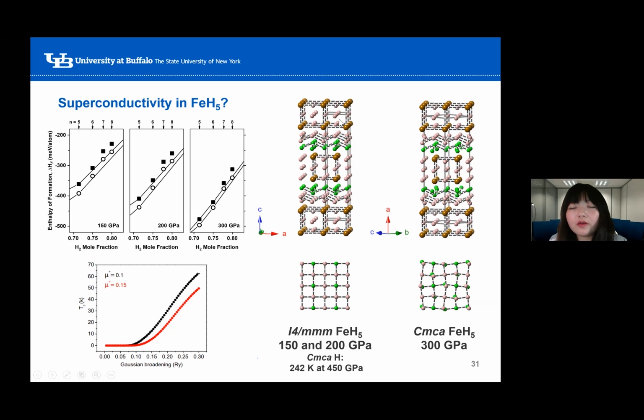FeH5 was also synthesized. And these layers are separated by atomic hydrogen layers, and the projection of the atomic hydrogen layers is shown here. So the major difference between these two structures is that in the I4/mmm, the H-H-H bond angle in the projection is either 90 or 180 degrees. But in Cmca, the network is distorted, and therefore gives it a smaller volume and smaller PV contribution to the enthalpy.